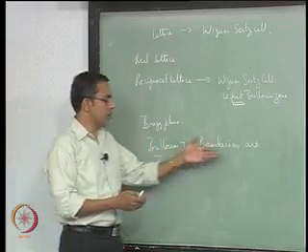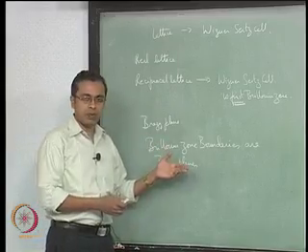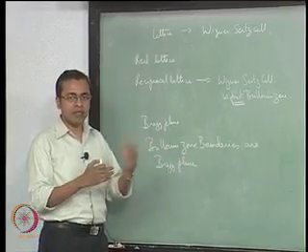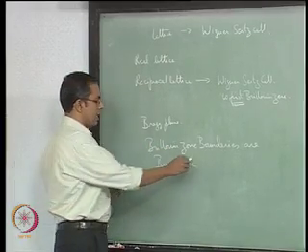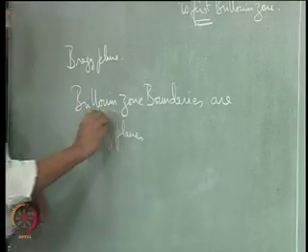So we originally defined Bragg plane independently, then we used it, and that is how we defined a Brillouin zone. But now having defined it, we understand that in any structure when I identify the Brillouin zones, effectively all the boundaries of those Brillouin zones are Bragg planes, and if it is the nth Brillouin zone, then at the boundaries we have crossed n minus 1 Bragg planes, we have not crossed the nth Bragg plane. So that is how the Brillouin zone is. So effectively the Brillouin zone boundaries are Bragg planes. So this is a very important piece of information that you should keep in mind.